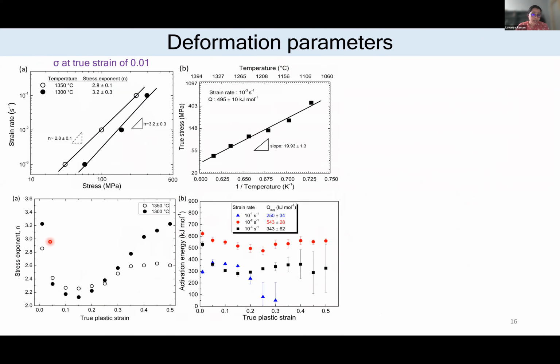When we did that, we can see that the stress exponent varies with increase in the plastic strain. It decreases up to a certain level and then it increases. Whereas the activation energy in low strain rate conditions is almost stable, but at higher strain rate condition, it goes to a peak and then decreases. So this clearly tells us that the flow stress is a strong function of your deformation temperature, strain rate, and strain. This is a classic behavior of any BCC alloy.